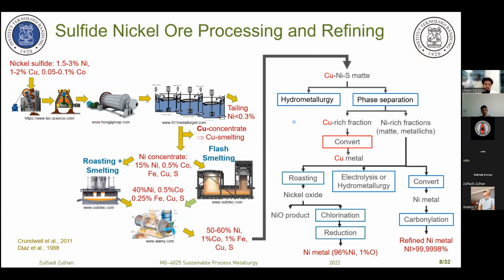Maybe you have gotten from the lecture before about the processing of sulfide nickel ore. If you see from this diagram, this flow chart, the first is the nickel content in the ore, around 1.5 to 3%. This content is increased to around 15%. Nickel in this case is in the form of concentrate. And we also get copper concentrate, which is sent to the copper smelting.